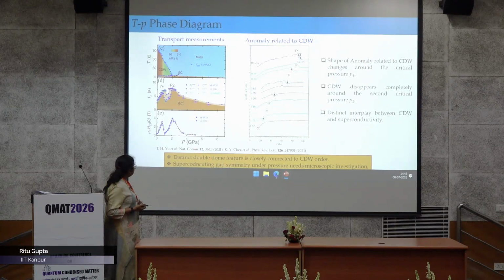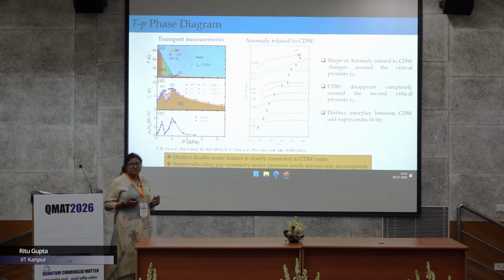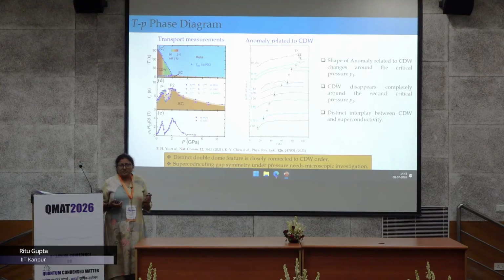So also they have plotted this dρ/dT as a function of temperature. So this step like feature around the charge density wave transition changes to a dip like feature around the same critical pressure. So that means it has something to do with the charge order phase.